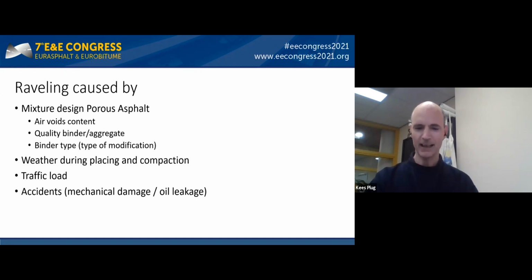Traffic load, more traffic and heavy traffic, will show more damage of the road. Accidents will give mechanical damage and oil leakage. Especially oil leakage will weaken the mastic and cause damage in the long run. After cleaning, there is no damage, but suddenly the asphalt will fail sometime.